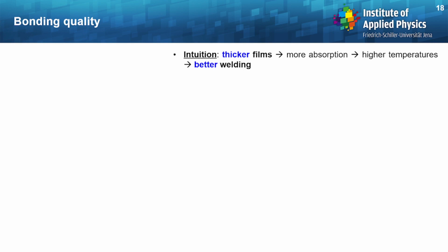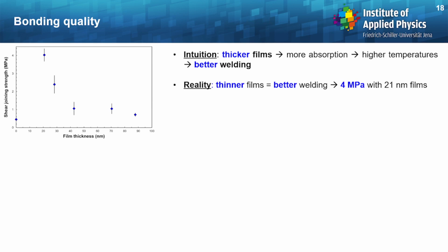Intuitively, one may think that thicker films would lead to more absorption, right? Because there would be more metal, and then higher temperature should be reached, which would lead to better welding. And experimentally, in reality, it's actually the opposite. Thinner films lead to better welding. And one can reach around 4 megapascal for 20 nanometer films, as you can see here, for the shear joining strength as a function of the film thickness.